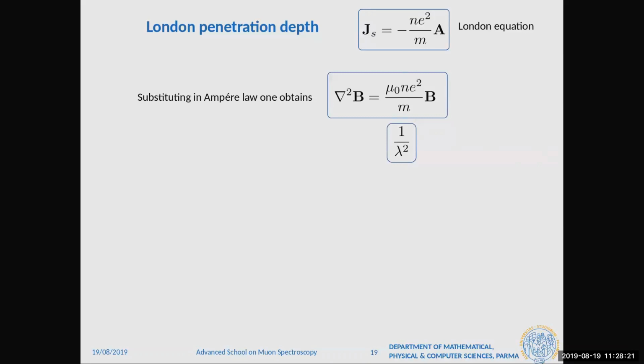It's very simple. It tells us that the Laplacian of B is proportional to B through a constant. The Laplacian of B is the derivative with respect to twice a length scale, so it must be the field divided by the square of a length scale. So this is the square of the length scale, and it's the length scale that controls how B penetrates the sample. So we call it 1 over lambda squared, right? And this defines lambda, simply because of dimensional constraints.